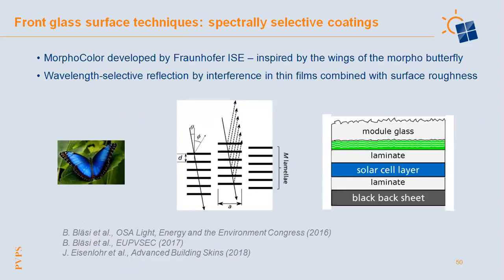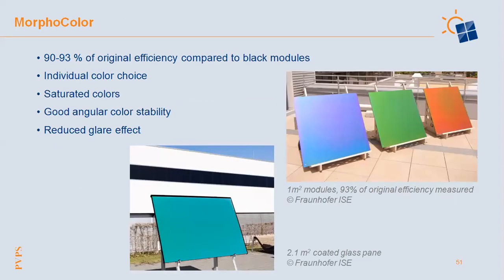Then a second technology developed by Fraunhofer ISE, the MorphoColor, is also a type of spectrally selective coating. It was inspired by the Morpho butterfly, and they use wavelength selective reflection by interference in thin films and combine it with a special surface roughness. As you can see here, you get very saturated colors with different individual color choices. And here you also have 90 to 93% of the original efficiency of the module compared to a black one. What is also worth mentioning is that it has a very good angular color stability and a reduced glare effect due to the rough surface.